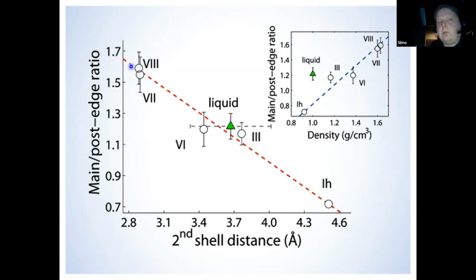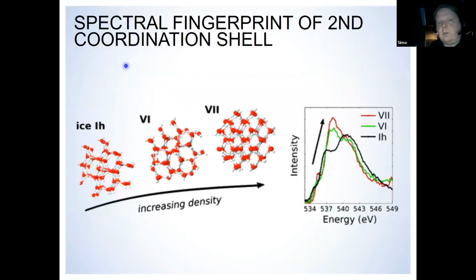So now we could say that basically the spectra correlate very well with the second shell distance, and we could then make a conclusion that the second shell distance is one of the key parameters. And I think that was a nice example of what one can do with X-ray Raman spectroscopy.